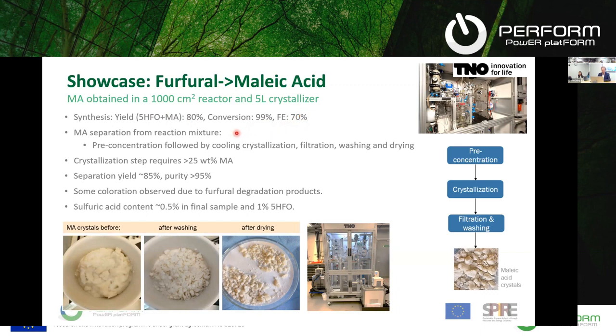We showed that we can do the separation, the pre-concentration, the cooling crystallization, and we got quite some purity here. You see after several steps that after drying you can get these still slightly brown maleic acid crystals. So it's not 100% pure, but it's very good quality already.